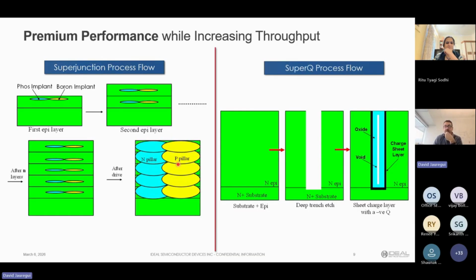Typically, vertical power MOSFETs or vertical power devices are in the range of 8 to 12 mask steps. That has traditionally been the target for these power devices to balance that cost performance metric. Today, our estimate is that the latest and greatest super junction structure by Infineon is around 28 to 32 mask steps, which makes it very expensive. Compared to what we're doing, our technology starts with bulk epi. We etch a trench, we line it with this charged dielectric, which I'll talk about in a bit, and then we fill it with dielectric. That's it. And so that's how we balance that cost performance, meaning that we manufacture a product that gives the same performance with higher manufacturability throughput and lower costs.